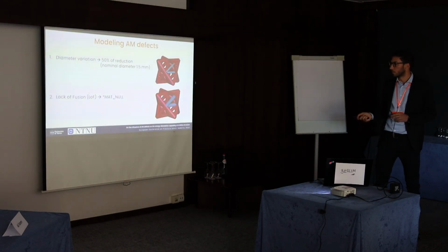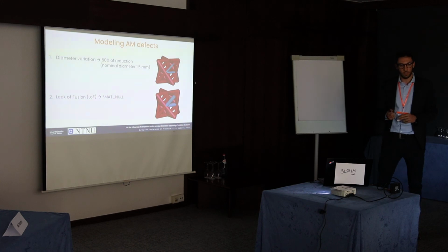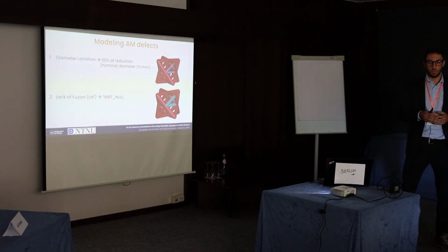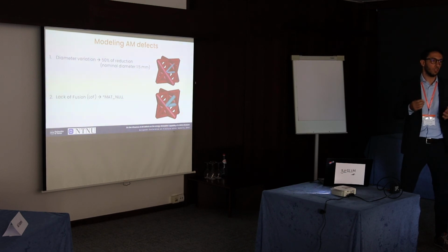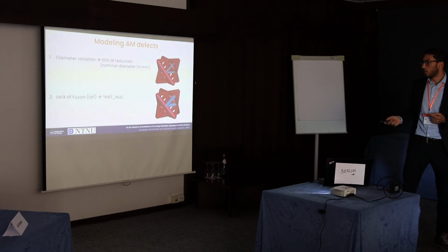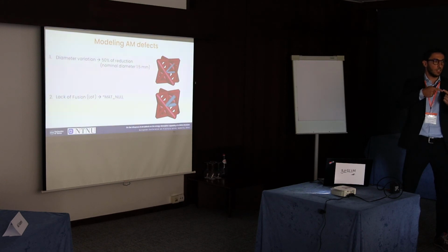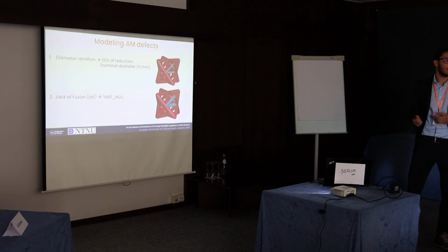Yeah, in a simplified way, we started thinking that when you have a lack of fusion in these very small beams, you can assume that the beam is a sort of disconnected beam. This is a discontinuous beam, and instead of making the beam discontinuous, so duplicating the nodes, we decided to use this material, the MAT_NULL, that is going to work in the same way because it is not absorbing any energy, and if the structure is discontinuous, the load will not transfer, and so it will not absorb any energy. It's a broken beam. Yeah, more or less the same. However, we did it with this material, and it works in the same way.